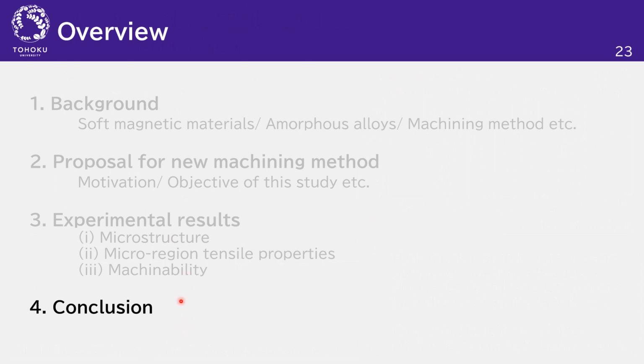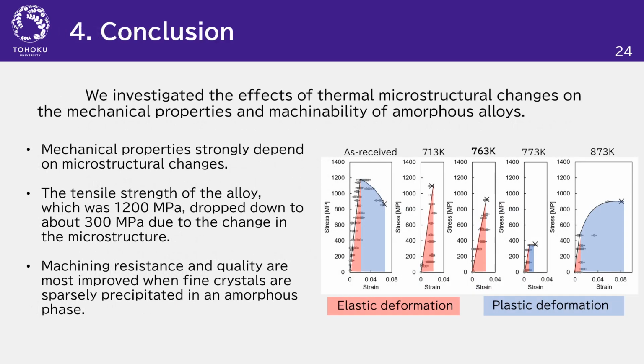Finally, we summarize this study. In this study, we investigated the effect of thermal microstructure changes on the mechanical properties and machinability of amorphous alloys. We found that mechanical properties strongly depend on microstructure change. The tensile strength of the amorphous alloys dropped due to the change in the microstructure. And machining resistance and quality are most improved when fine crystals are sparsely precipitated in the amorphous phase.